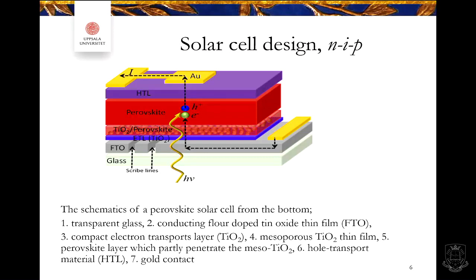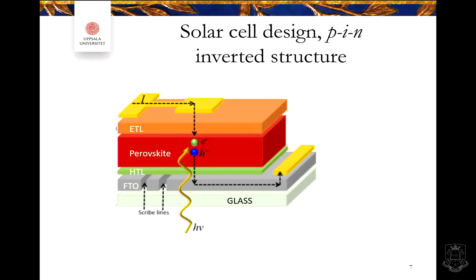They can also be called inverted, so PIN instead. Then, simply described, the hole transport material is the first layer that is deposited on the conductive glass, and then the perovskite, then the electron conductive layer, and then a metallic contact, many times silver in this case when you have the inverted structure. And you will hear about inverted, both the normal structure and the inverted, later on.